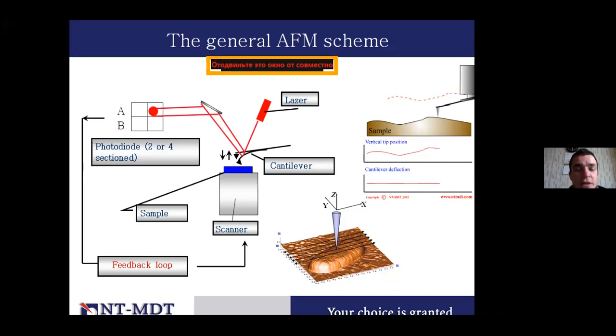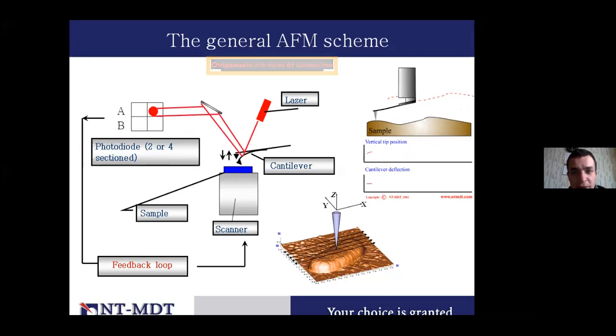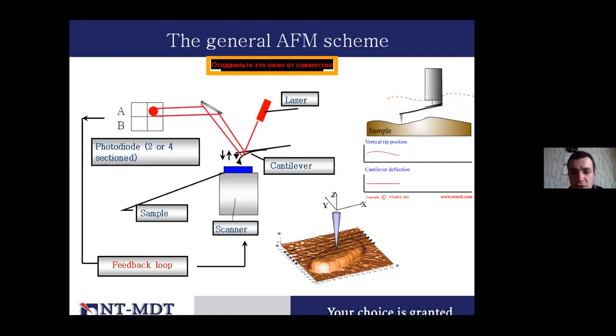Depending on what we need to measure, topography or some properties, we can arrange different types of feedback loops, to measure topography, relief, and so on, or electric, magnetic, lateral, friction properties, and so on. On the right, you can see a small animation of how the sample and tip interact. For example, you can see how the scanner follows the sample. We measure the vertical tip position, and our feedback loop keeps the deflection of the cantilever constant by moving the scanner up and down. This movement of the scanner up and down, we interpret as topography in our case. As a result, we can obtain such an image, which you can see in the center below, an image of some structure shown in 3D.